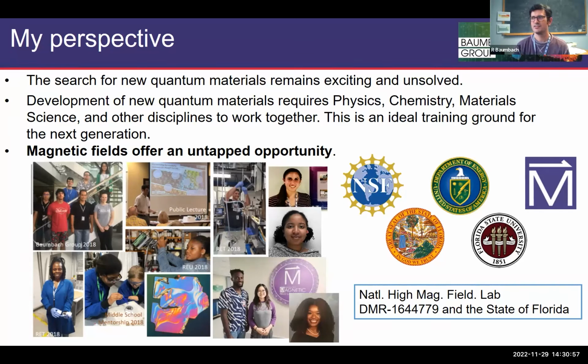Fantastic question. So the answer is it depends on the material. Uranium ditelluride is very susceptible to moisture, air, so it degrades. Even if I seal it under vacuum and store it in a quartz tube, it just degrades. That material is very, very sensitive. Other ones, we grow all sorts of silicides and aluminum things, and other ones will last forever. So it really does depend on the particular chemistry of the material.